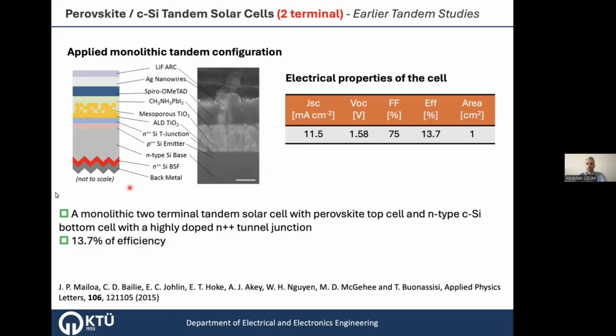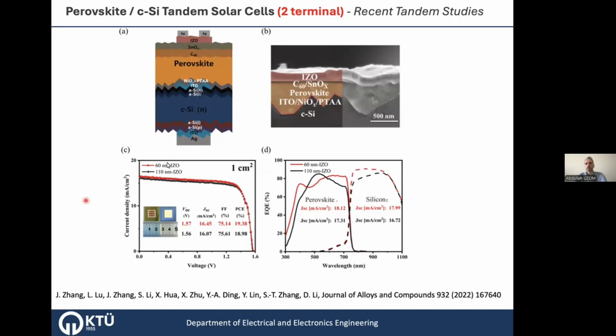One of the monolithic devices in tandem solar cells. If we come more recently, you will see that almost the cell is similar with the crystalline silicon heterojunction solar cell, mainly because of the high efficiency. You can see different recombination junction trials, like nickel oxide topped with a PTAA layer maybe. And here are the views of the SEM images, and with this monolithic, again, these are monolithic two-terminal devices, you can reach an efficiency of more than 19%. And these graphs you will see in others too. These graphs show the absorbance capability of the perovskite and silicon parts, so you can see how much current you can have from each device.